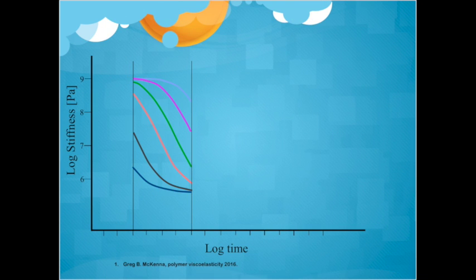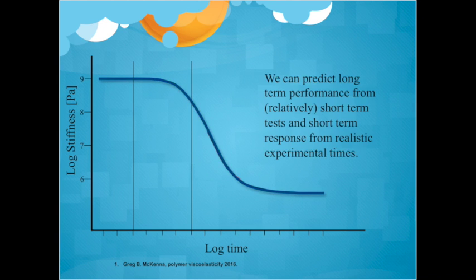Here, we will introduce a concept, namely time-temperature superposition. The relaxation function doesn't change shape with temperature, but does change position in time. So, high-temperature short-time experiments are equivalent to long-time experiments at lower temperature. So, if we shift the curves one by one, we will eventually get a master curve. That's exactly what we want. And this principle can be used as a powerful tool to describe material behavior outside of the normal experiment window.